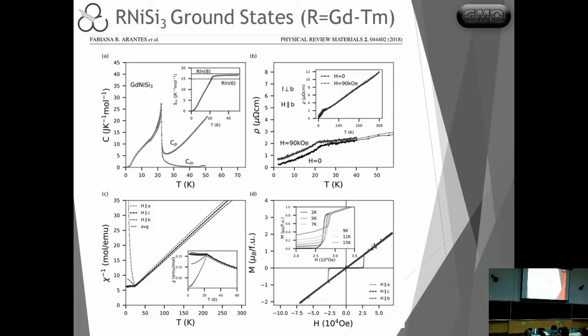And in the case of gadolinium, as you usually expect from the half-filled shell, you don't have a lot of anisotropy in the paramagnetic state, but as soon as you transition into the antiferromagnetic state, then there's a clear anisotropy here, which shows what is the favorable direction of the aligned moments. In this case, it's the A axis, which is the preferential aligned moment here.